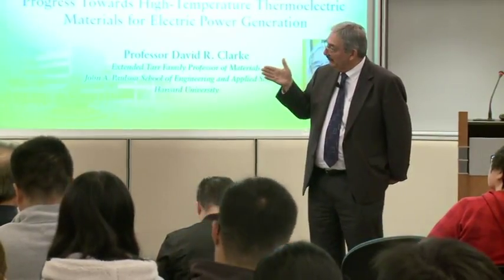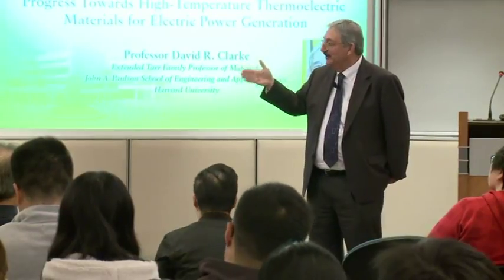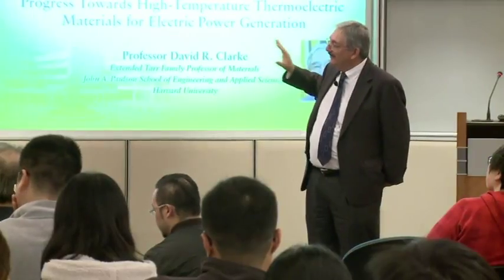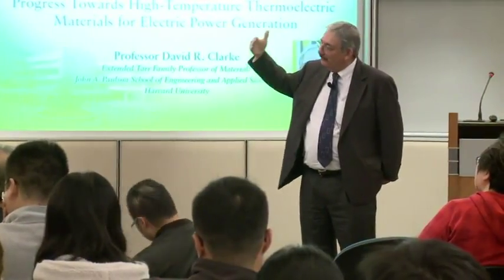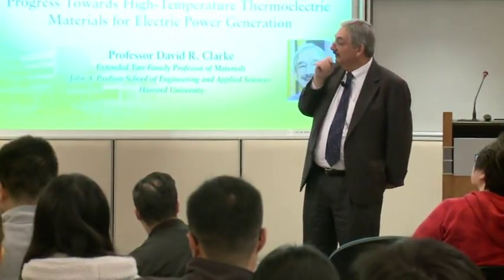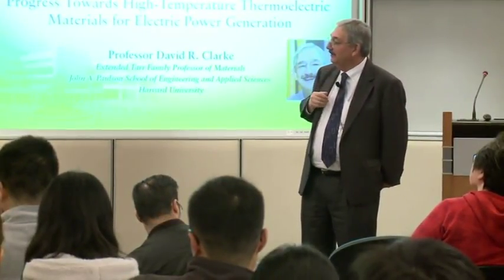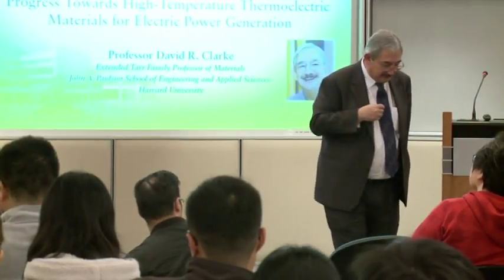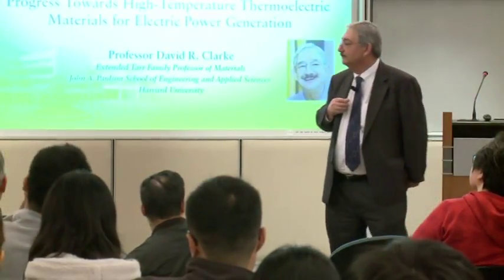You can measure the energy, and you can relate this to the band structure. The image I showed you actually had the band structure of the zinc oxide, but not knowing all your backgrounds, I left that out. But the bands that we see in the low energy Raman correspond to the zone foldings that we would expect from the phonon spectrum.